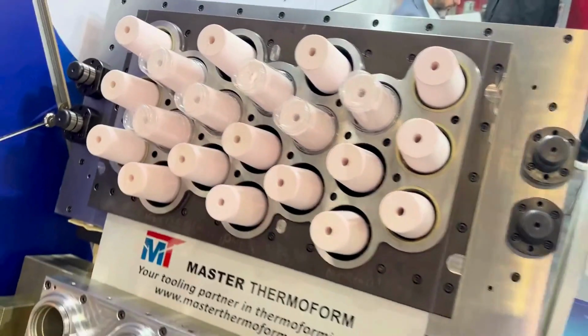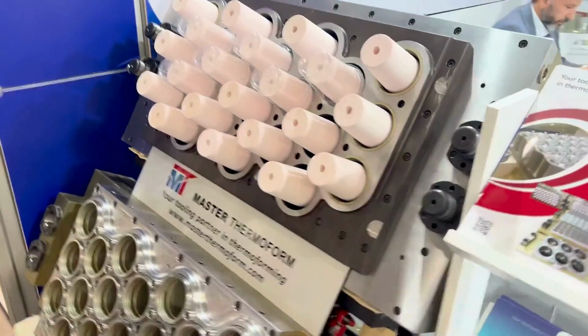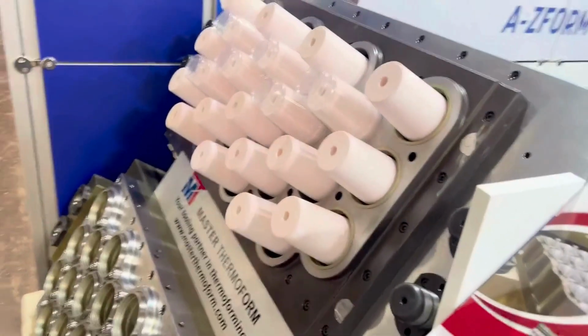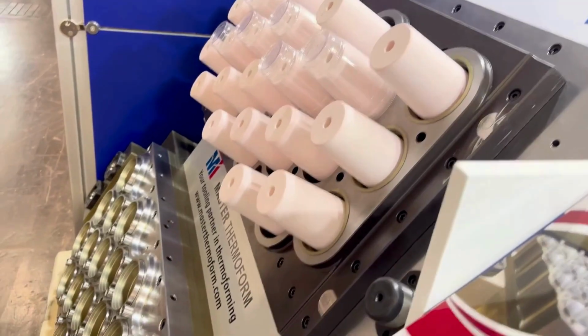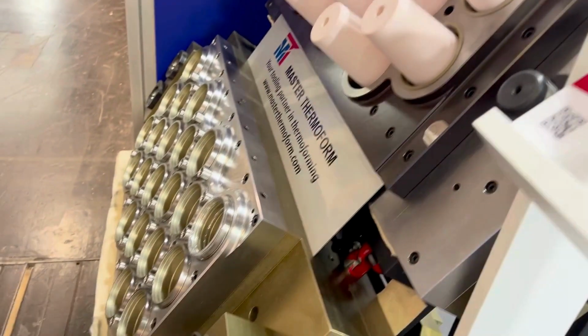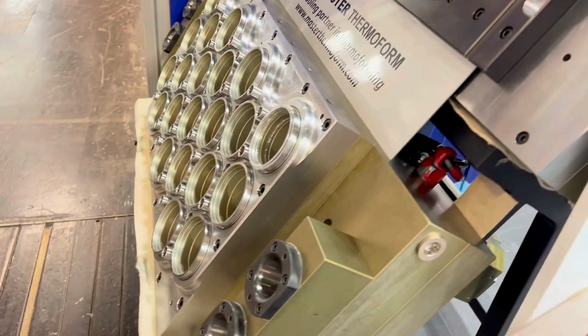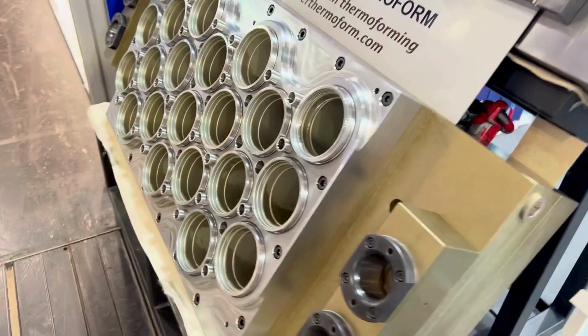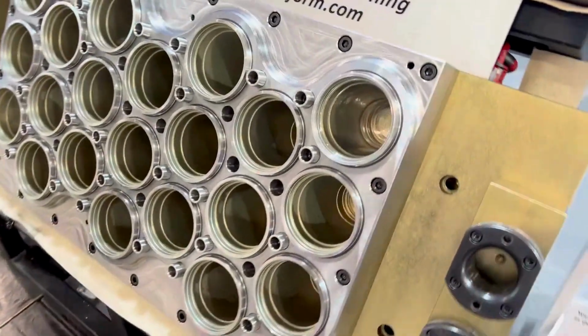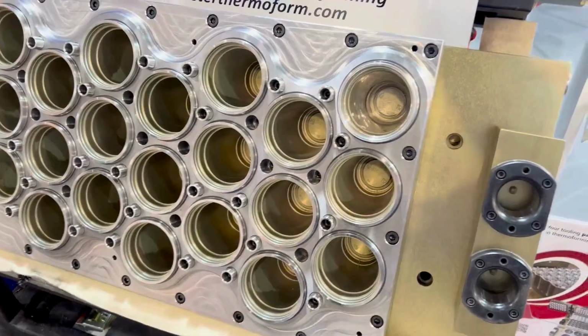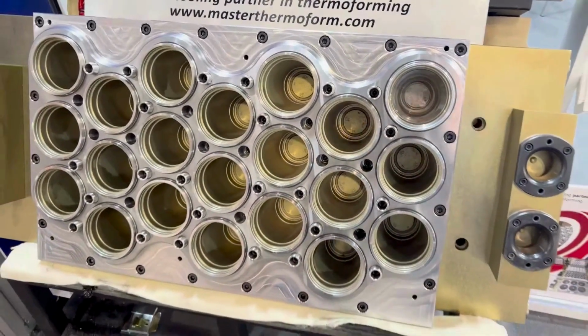A well-designed plug can also reduce common defects, like webbing, thinning, or tearing, because the deformation is guided rather than left to chance. That often allows manufacturers to down-gauge the starting sheet thickness, since the material is being used more efficiently and less margin is required to compensate for inconsistent forming.